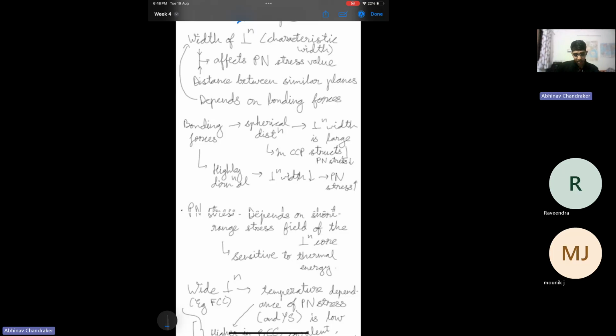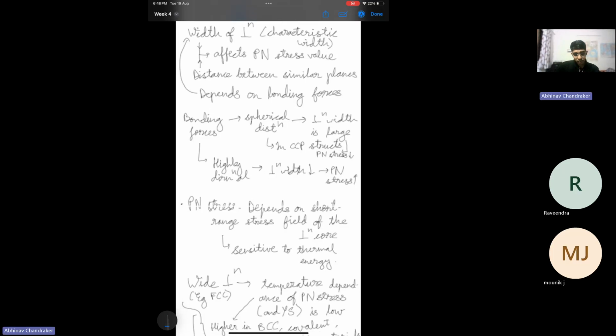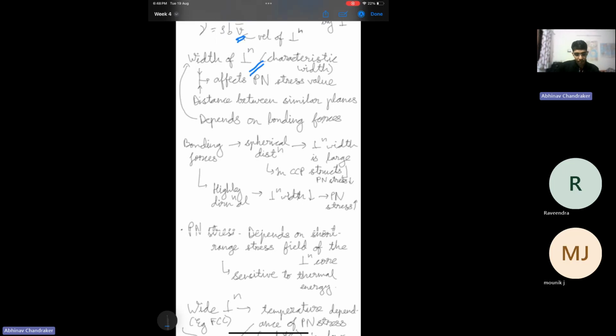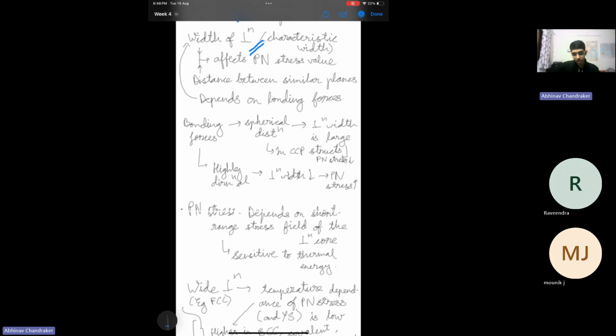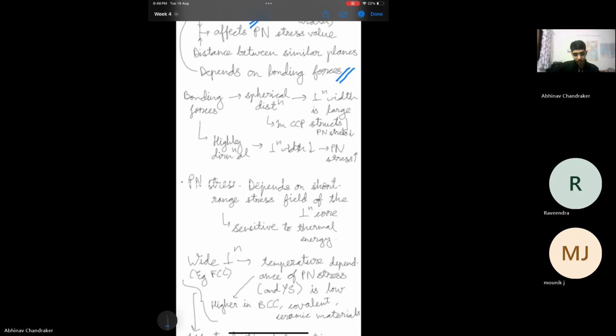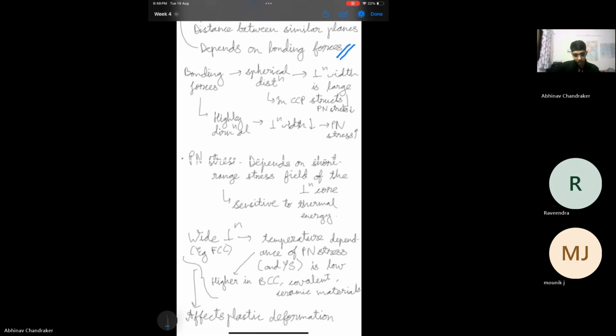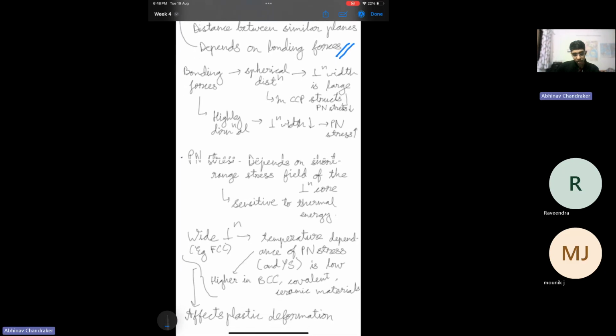As a result, the PN stress, Peierls-Nabarro stress, which is the stress required for a dislocation to move, will depend on the width of the dislocation, which in turn depends on the bonding forces. So if the bonding is such that there's a spherical stress distribution, then the dislocation width tends to be large, while if it is directional, then the width tends to be small, and PN stress is higher.